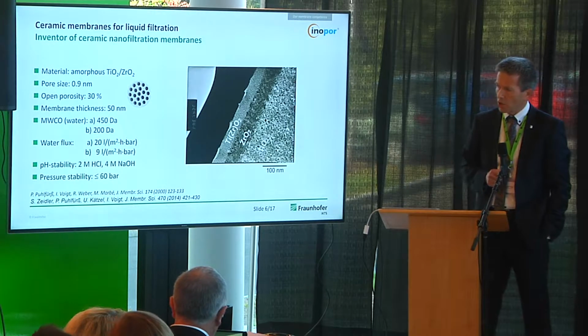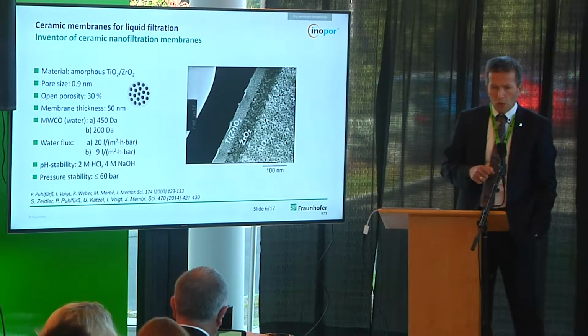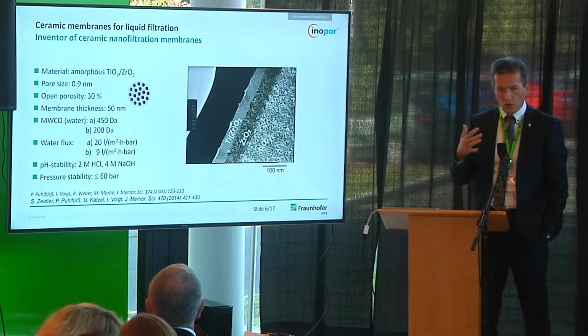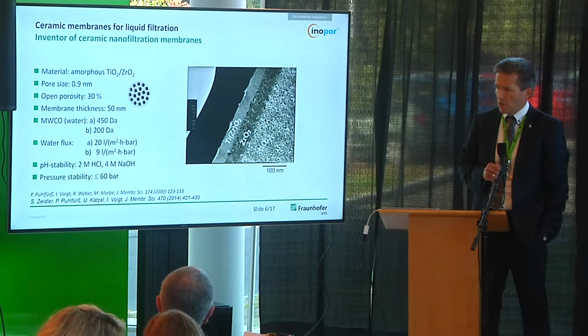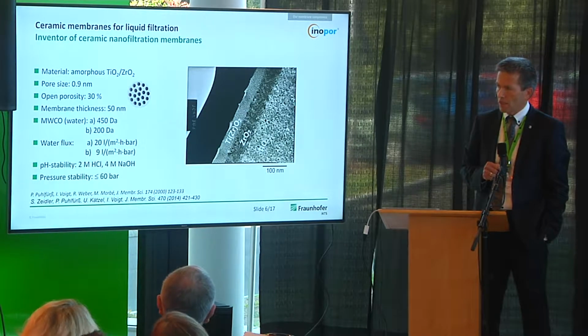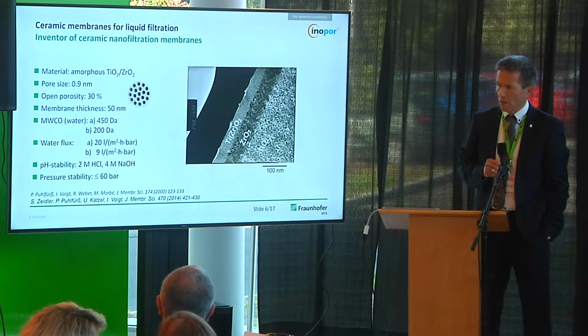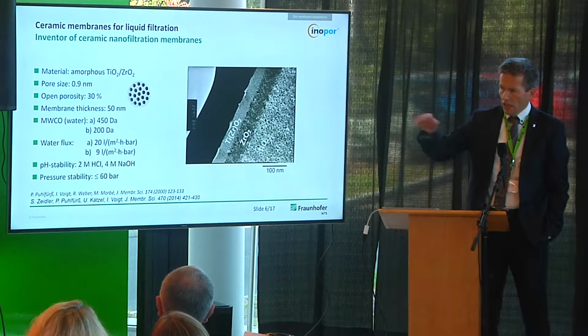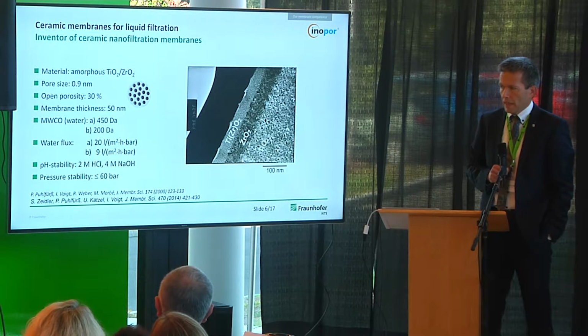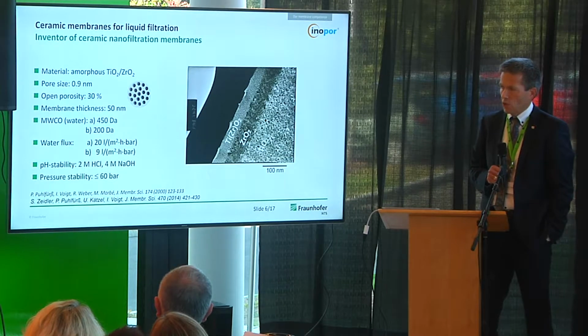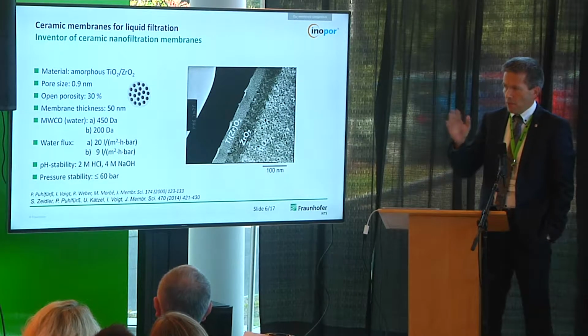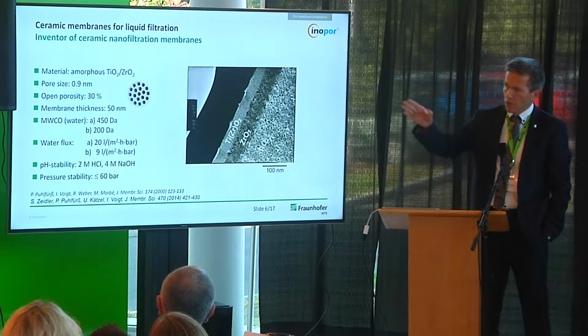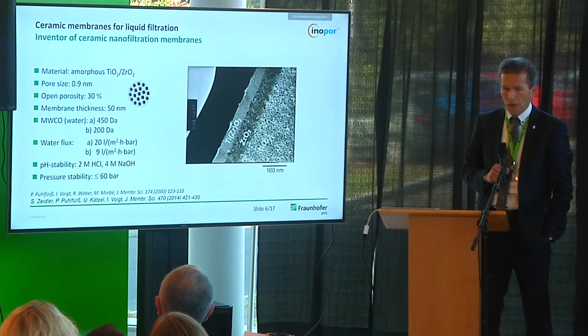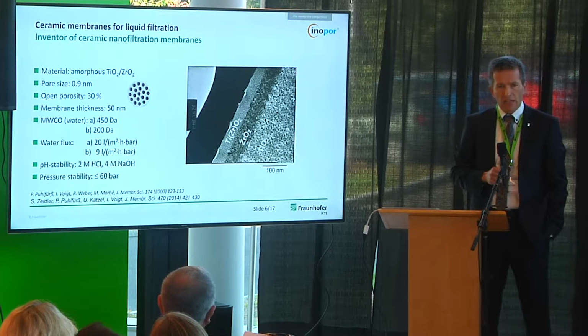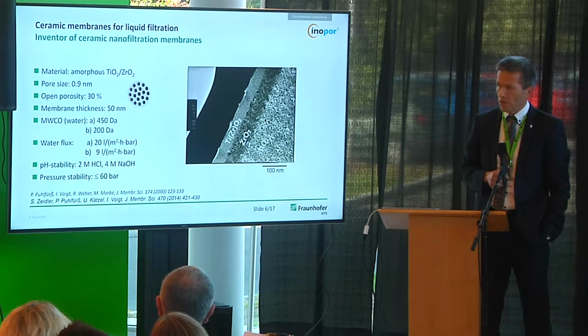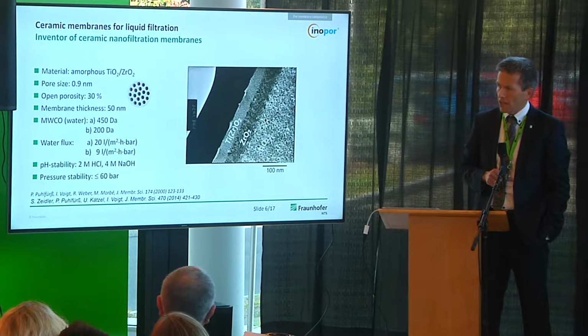We perform this coating here in the clean room to avoid any dust during coating and to control the humidity, because during preparation the membrane is sensitive to humidity. After heat treatment, after sintering of the membrane, it is very stable. You see this, the chemical stability in an acidic and alkaline solution. And this membrane was optimized for this 19-channel tube and is already in operation in about 50 different applications.